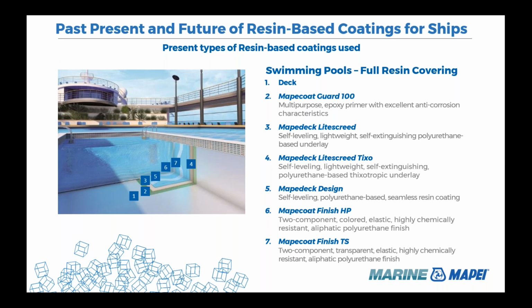After that, we have to apply 2 or 3 layers of a final coating, which will be the MAPEI Coat Finish TS, which is a transparent finishing. This is very important, and the reason why we apply more than one layer is that you should consider that a pool tank containing water is going to be attacked by the water, which is full of chlorine, and sometimes the ships use also salty water with chlorine. So this kind of water is going to be the most aggressive agent you can find on a pool. Next slide.